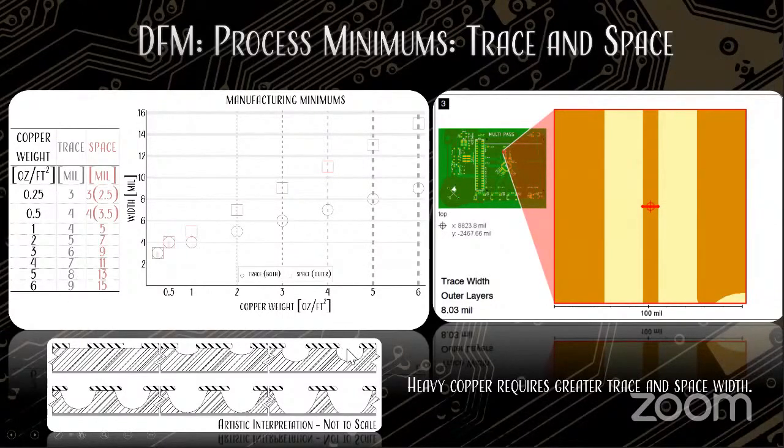Don't push it. See, when copper etches, it doesn't etch straight down from the mask. It kind of starts going in a little bit of a curve. And if you leave it in the etching tanks long enough, you get this slightly curved trapezoid. You have to really, really over etch it to get purely vertical sides, and it's simply not worth it. But that's something we sometimes see high-speed designers want because that's what they modeled. You have to over etch, which means you need greater spaces in between the traces, which then costs you space at the very end.